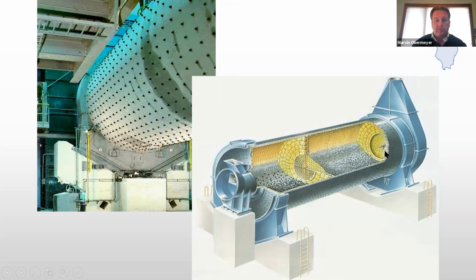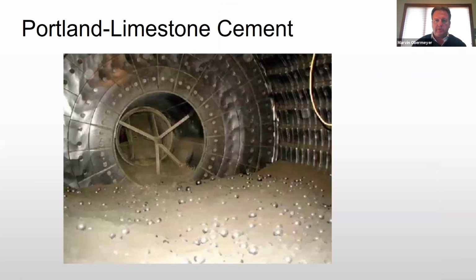So the difference between type 1 and type 3 cement, for example: we may have one of these running type 3 cement only, and the particle size would actually be smaller. So we would choke down that vacuum, so to speak.